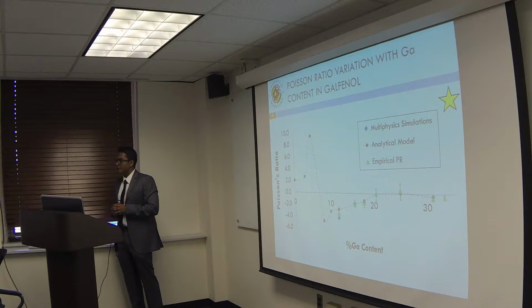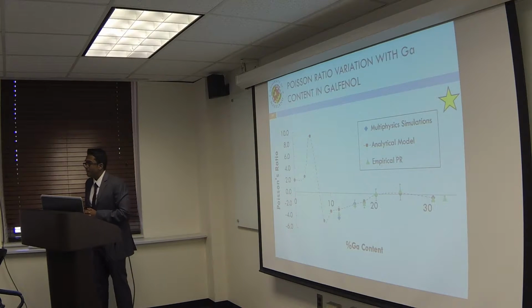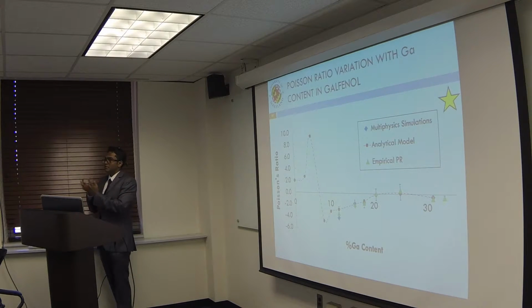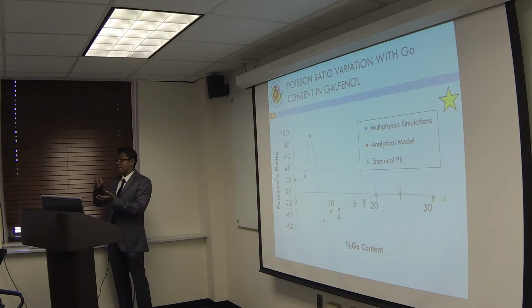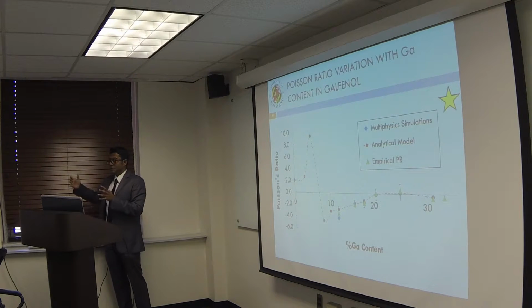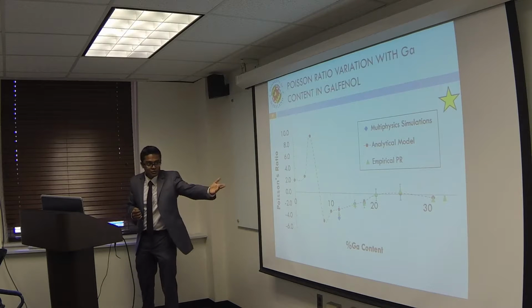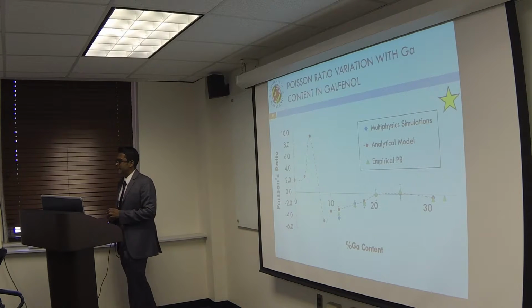What supports the idea of atomic ordering? Depending on which lattice points the gallium atoms occupy, that determines how much magnetostriction I would get. And that determines how much strain I would get along the longitudinal and the transverse 1 0 0 direction. And the ratio of that will determine the Poisson's ratio, which is what I'm presenting here.